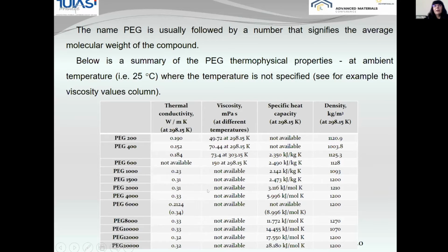And of course, the number that appears there signifies the average molecular weight of each compound. So the experiments that were identified in the open literature are limited to PEG 1000, because after that, if we increase the molecular weight of the compound, the viscosity increases too much. So they cannot be used as fluids.